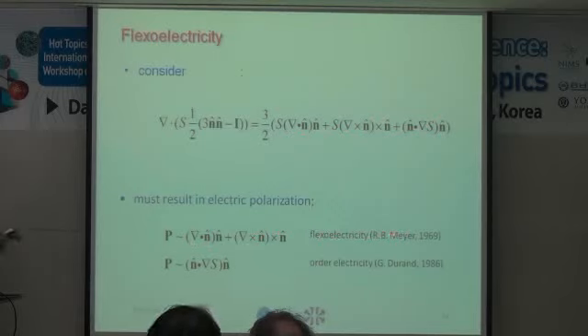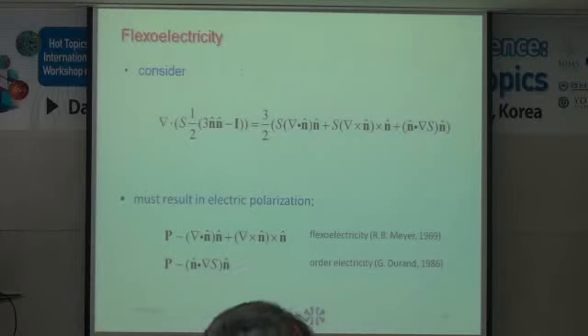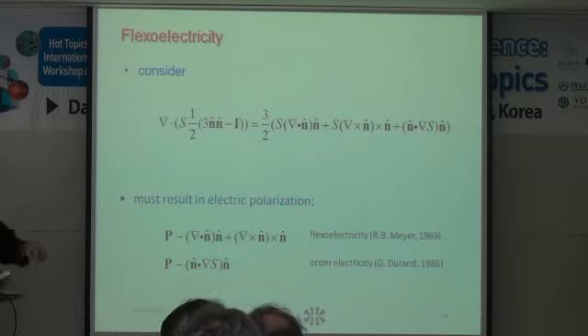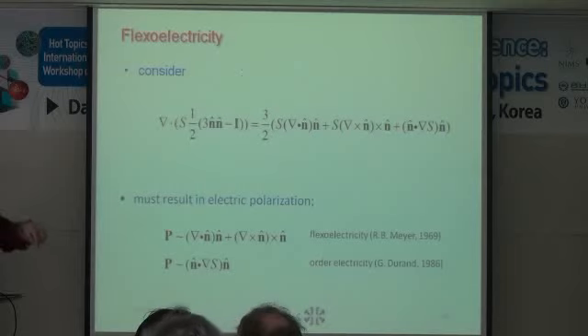So simply, if you have any kind of spatial variation of n, then there will be electric polarization as a consequence. And even if you have a spatial variation in the scalar order parameter, you must have electric polarization. So if you take a liquid crystal and you heat it locally just a little bit to make the order parameter a little lower in value here than here, then there will have to be electric polarization arising as a consequence of that. So I think there's a lot of interesting complex possibilities.